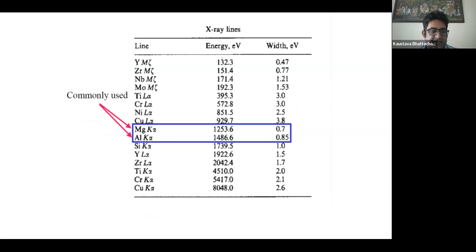In XPS, what we do is we deconvolute the peak and try to find the oxidation state, or the DOS, that is the density of states, from that. So my source should be such that I can do the deconvolution, and the differences we need to resolve are in the regime of 0.1, 0.2, 0.3 volt. So the line width of my X-ray source should not be more than 1 electron volt. That's the reason we choose aluminum and magnesium K alpha, where you can see the line width of aluminum and magnesium is 0.85 and 0.7.